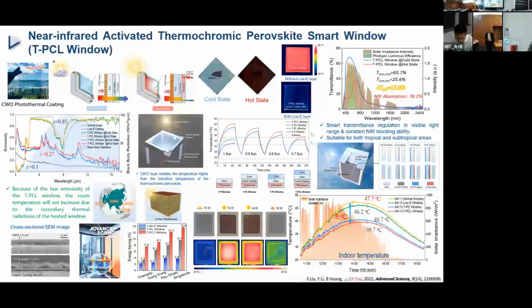We built four model houses. The first one has a normal glass window, the second one a low-E window, the third one the perovskite window without the low-E coating, and the last one the TPCL window. We conducted tests in the local Hong Kong climate, and we found the indoor air temperature in the model house with the TPCL window is about 8 degrees Celsius lower than with the normal glass window. We can save at least 10% of energy consumption.